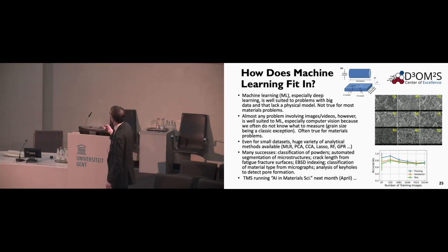But if you use a certain fraction of these images to train a network, and you ask the network to predict for a validation set, how well can you predict that a given image was from a transverse direction versus a rolling direction, the validation accuracy can be as high as 80%. So it's not a slam dunk, but it's doing pretty well. I'm showing this to you to get you to exercise your imagination, that this is a pretty good example of where ML can really help us as materials scientists.